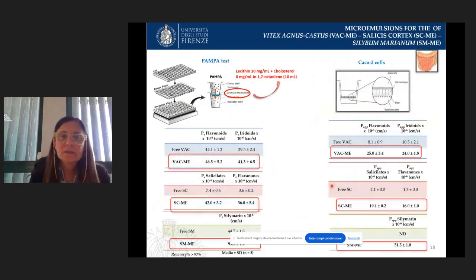About the influence of the formulation on the in vitro permeability, we performed the PAMPA test and also the test in the presence of CACO2 cells. CACO2 cells produce a layer similar to the intestinal barrier, with cells similar to intestinal cells in the layer. We calculated the permeability coefficient, Pe in the case of PAMPA and Papp in the case of the CACO2 cell study, and we observed that the formulations improved the in vitro permeability for all three extracts with respect to the extract in water.